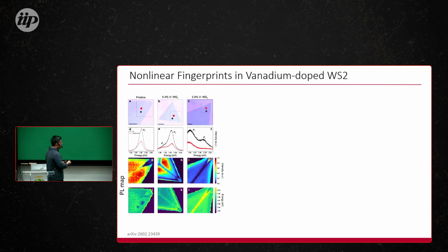So we perform a mapping. We select this area you can see here, and for each point we collect this kind of spectrum, and then we can plot this map. This is the intensity of these peaks, and here is the energy, which is the position of those peaks. We can see that it starts to show this line, and this line lies exactly along the bisector.